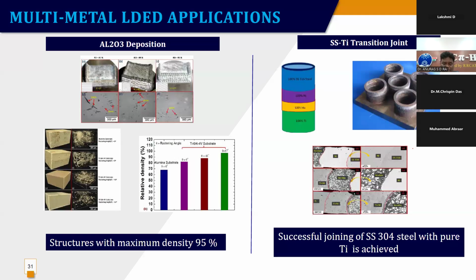So that was done. We also tried to build an SS titanium transition joint. Here, direct deposition of SS on titanium is not possible. Then we had some interface alloys, worked on these metals, and then things came up. And this is done smoothly, very nicely.